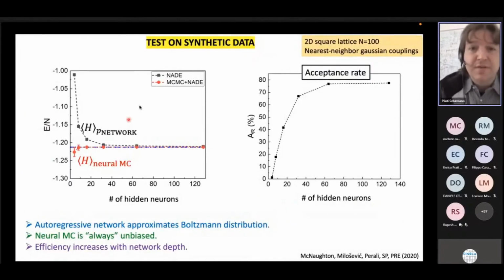So let me show some data first, working on synthetic data, so data generated by a classical Monte Carlo simulation. And here, these examples are shown for a relatively small system, just a 2D lattice with 100 spins. And you see the average energy that you obtain as a function of the depth of your neural network, in particular the number of hidden neurons that you have in the hidden layer of a neural autoregressive distribution estimator. And you see that even the energy that you obtain by doing an expectation value over the model distribution, in black, converges to the exact result, which means that the neural network is learning to approximate the Boltzmann distribution more and more accurately.